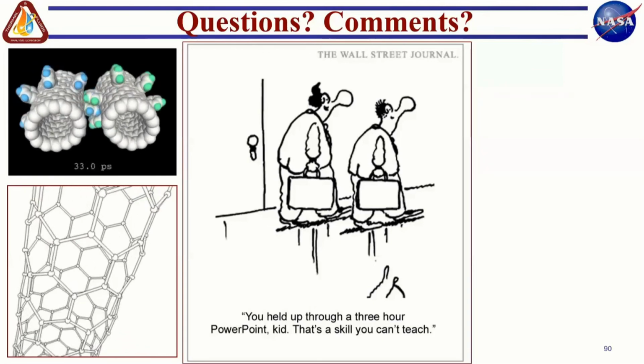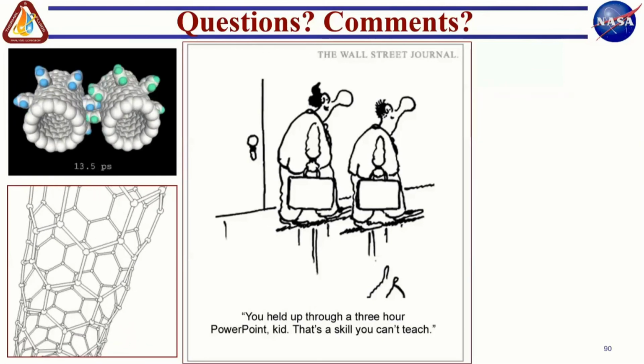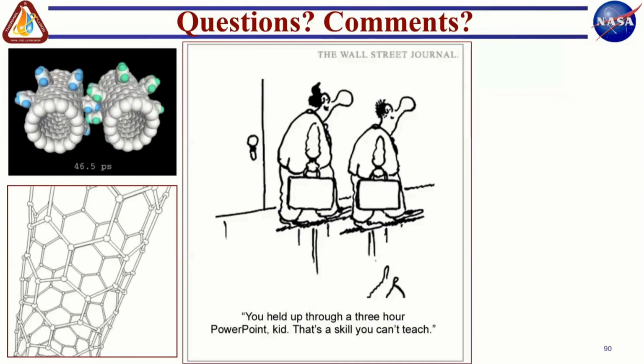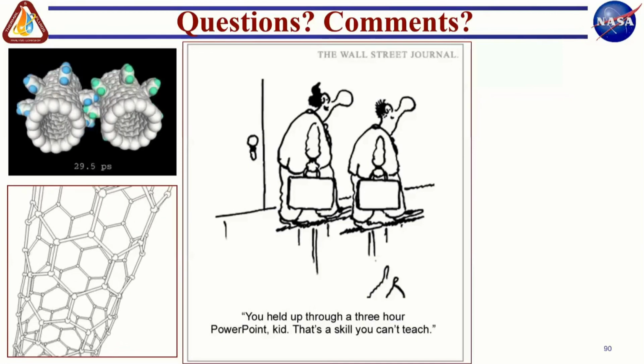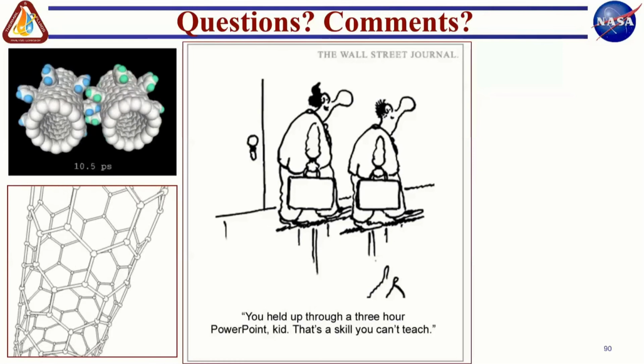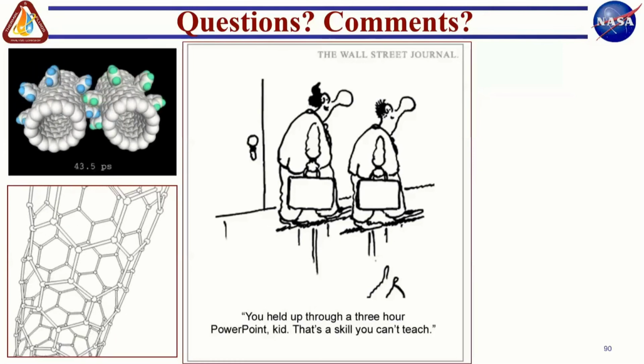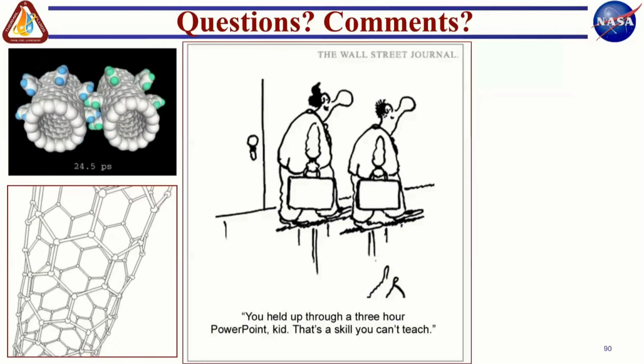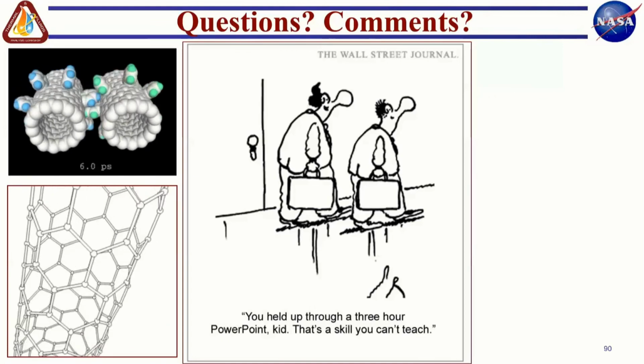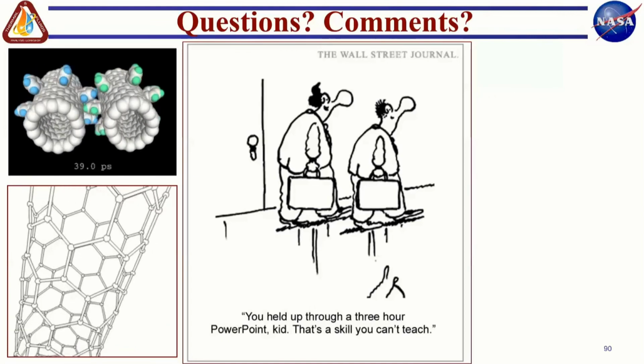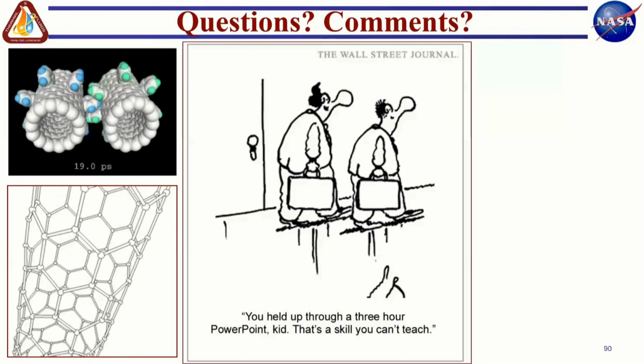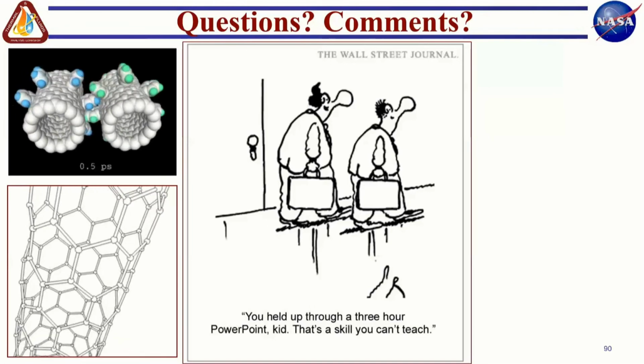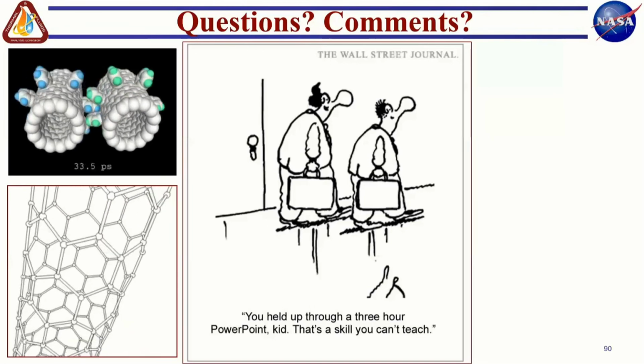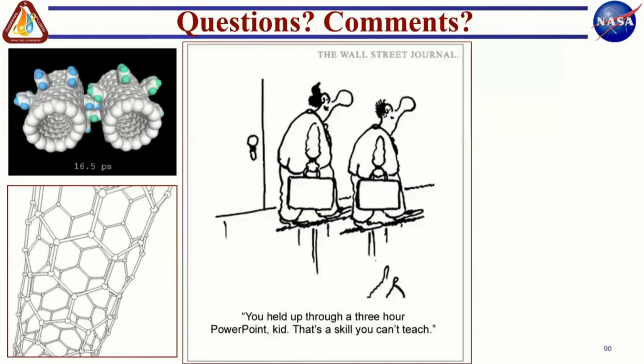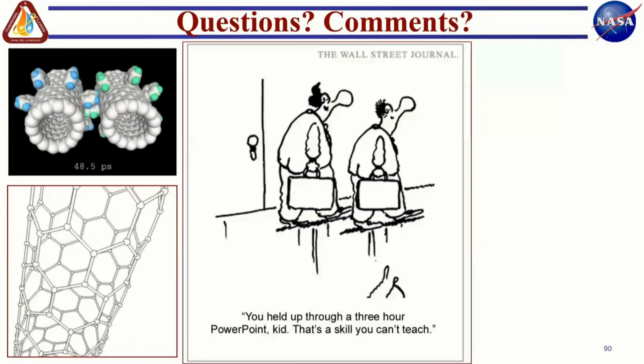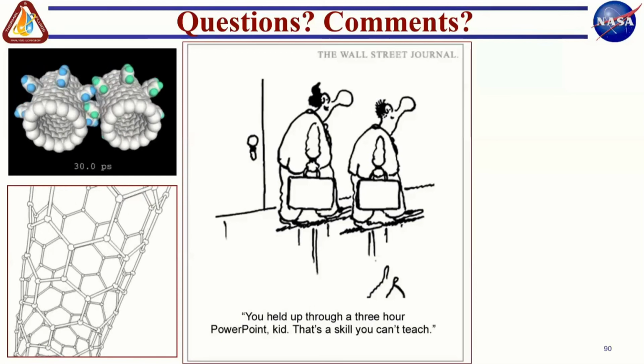I didn't get time to talk into that, and this is one of the reasons I'm so grateful to Air Force Research Lab. Because when we were doing the experiments, I got hold of people in the materials directorate, and they helped me to surface functionalize the carbon nanotubes with amine groups, and I'm trying to remember. There were a couple of surface functionalization strategies we took, but they advised me to do that, and that was a very good advice, because carbon nanotubes typically don't want to get into hydrogen bonding.